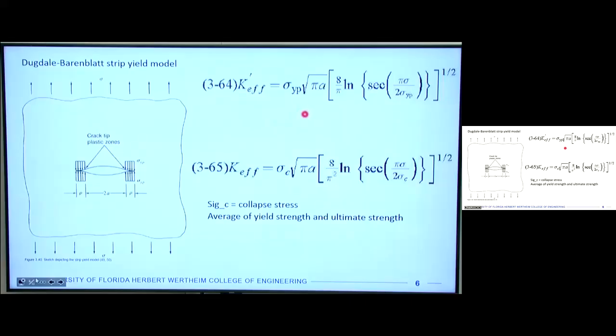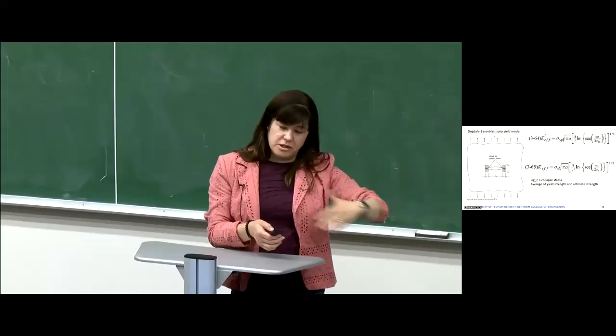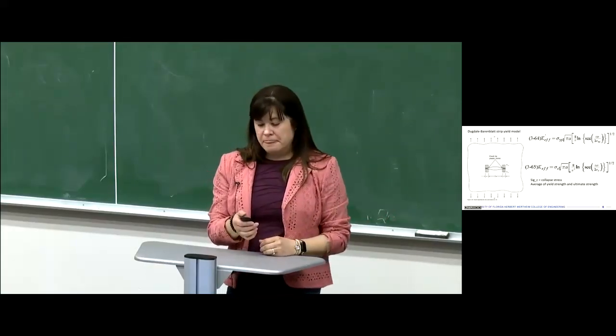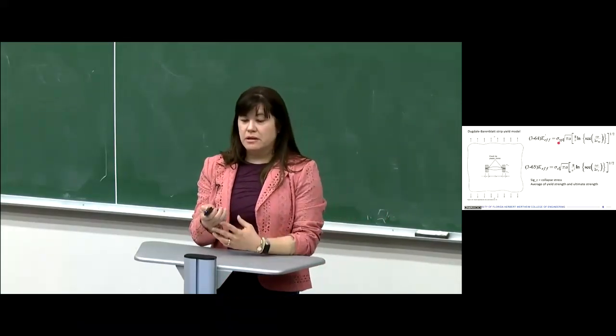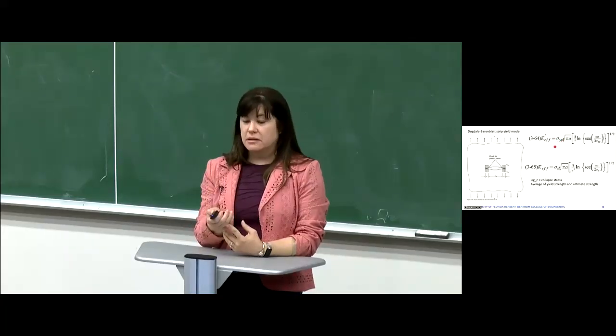And as a first pass, we can just put in the yield point here because we can assume that yielding is happening here. But in a real instance, and what we know from basically chapter 6, is that we can put a tensile specimen in and pull it, or put a component under a 3D state of stress that continues to increase, and we can push it past the yield point into plastic deformation up to the ultimate strength, right? And so instead of using the yield point in this equation, a more accurate value to use would be what they're calling a collapse stress. And so that's this sigma c.